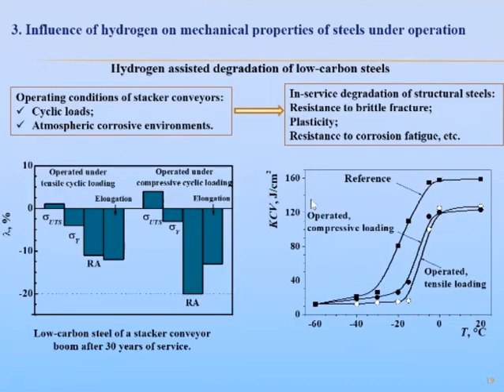Here you can see another example of hydrogen-assisted degradation of carbon steel under operation and dependence of steel degradation degree on the sign of operational cyclic loading. The material under study was low carbon steel obtained from a stacker conveyor boom after 30 years of service. This boom frame of a stacker conveyor was subjected to atmospheric corrosion and operation. And as it was shown, atmospheric corrosion is accompanied by hydrogen erosion.